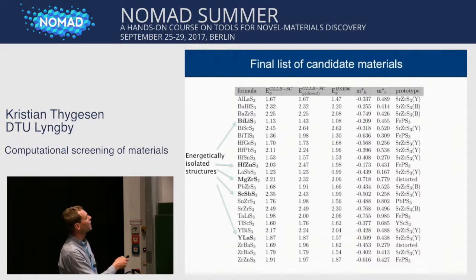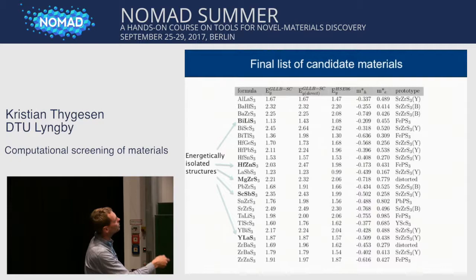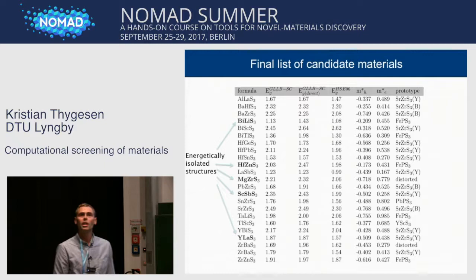This is the HSE band gap, as you can see over here for comparison. These are the effective masses, and this is the structure prototype that came out. Some of the materials up here are highlighted in bold. That's the material where there is only one structure that is significantly more stable than all the others. Okay? So that's where we are most sure that this is the structure that will actually come out if we try to synthesize bismuth lithium sulfide.